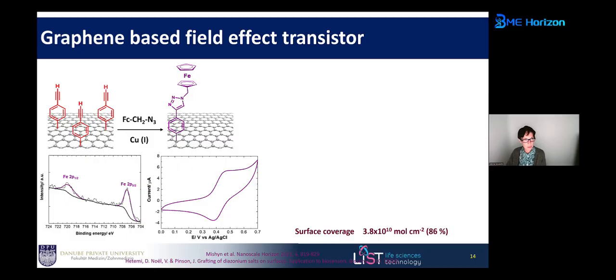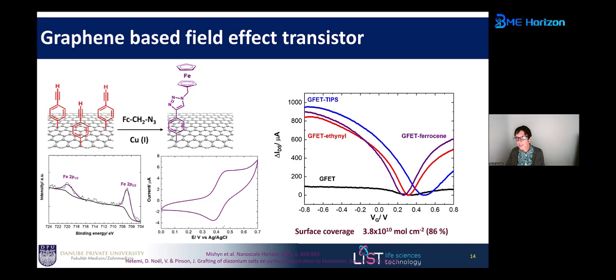So we did click chemistry on this graphene surface, and you easily see the integration of this ferrocene on the interface. And I hope I convince you with this charge transfer characteristic that we keep very high charge mobility. That means this process is very well adapted to get very sensitive gFETs for the sensing approaches.